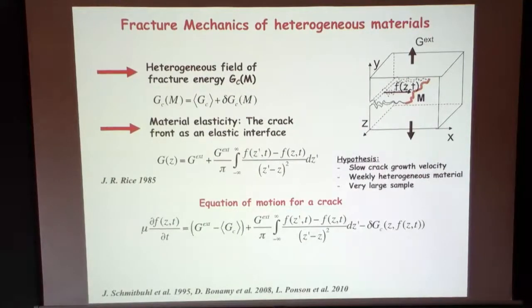Just a short comment, I hope you don't mind. Sure. This is perfectly correct as long as the crack is slow, so it can equilibrate with the boundaries, for example. That way, the velocity depends on how fast you're displacing the material, because the crack knows about it, because the time scale is the sound speed, to go back and forth in the boundaries. Things can get pretty hellish though if the material is overstressed, for example, if you're not locally conserving energy, but you initially put in more energy than the sample can deal with.